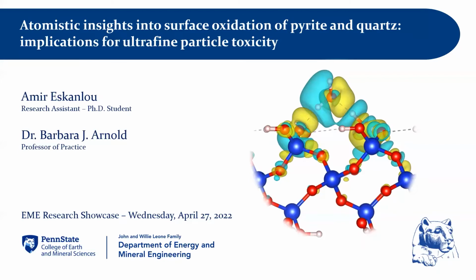So the approach is relying on the electronic structure of these particles. By calculating the electronic structure of this material, we can understand their behavior in the atmosphere and when they interact with water and oxygen molecules. So the objective is gaining atomistic insights into quartz and pyrite surface oxidation. This is important because the formation of free radicals as a result of surface alteration brings about the bioactivity of these particles. The approach is ab initio molecular dynamics simulation using quantum mechanics.